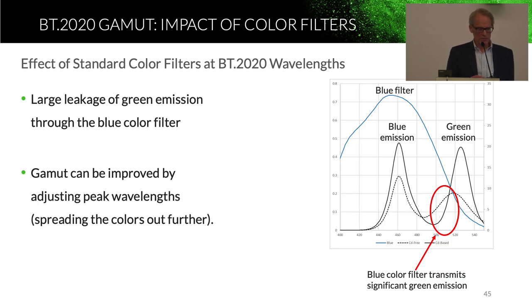And you can see that the green emission, whether it's from the narrower cadmium-based quantum dot or the cadmium-free, is overlapping heavily with the blue color filter. So in the blue channel, we don't only have the blue LED light, we also have a lot of the green light. So this is a problem. Maybe that would work if they were truly monochromatic emitters, but they are not. And quite frankly, the color filter is not in the right place.